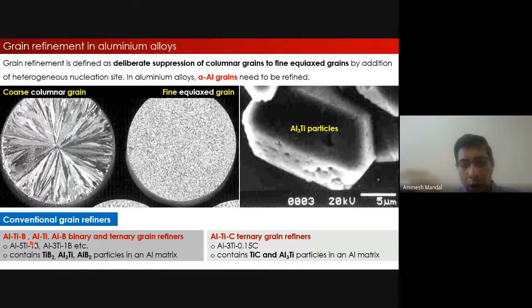So what does this alloy contain? This alloy essentially contains these particles, and when added to the molten aluminum, these particles act as substrates for nucleation of the alpha aluminum, and thereby you generate a fine grain material. So that's the basic understanding, and this mechanism is called heterogeneous nucleation.